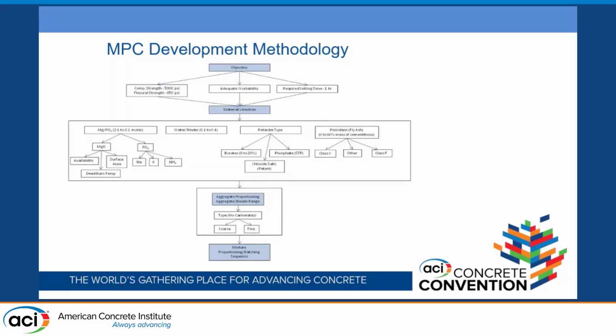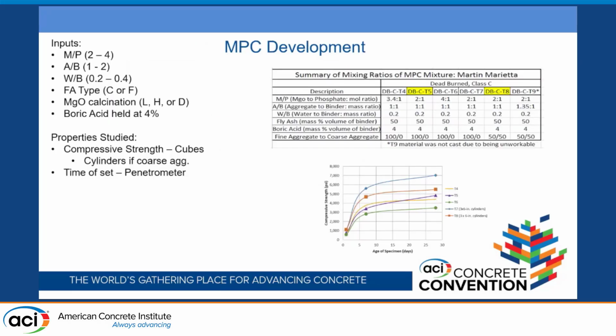done being mixed. And then we go through, we balanced a lot. And so we had inputs of kind of our factors in our design of experiments, if you will. Magnesium to phosphate ratio, and that's a molar ratio you see on the screen. Aggregate to binder ratio, fly ash, and then the properties studied, at least initially, were compressive strength of cubes, cylinders if we added coarse aggregates, and then time of set via the penetrometer.